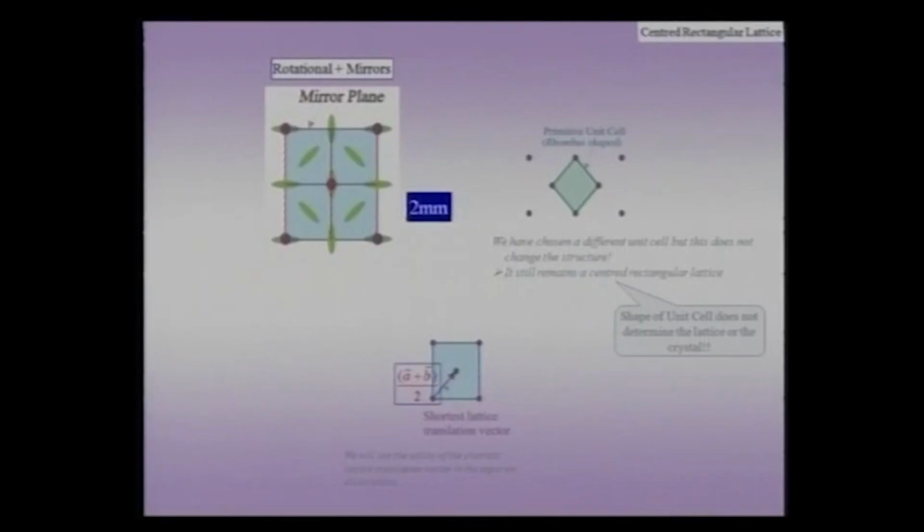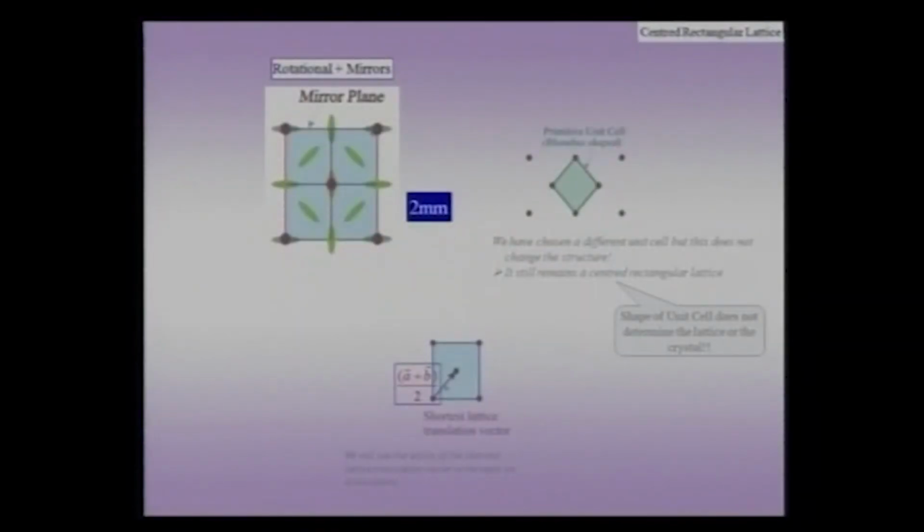And when we had dealt with the concept of unit cell, we had said that we could choose doubly non-primitive, triply non-primitive, and the choice is infinite, but those infinite choices in no way affect the kind of lattices which are possible in 2 dimensions, which is constrained to be just 5. So, there are only 5 possible lattices in 2 dimensions, and our choice of unit cells is infinite even for a single given lattice. But the preferred cell in the case of the centered rectangle is a rectangle unit cell, which has been shown in blue.